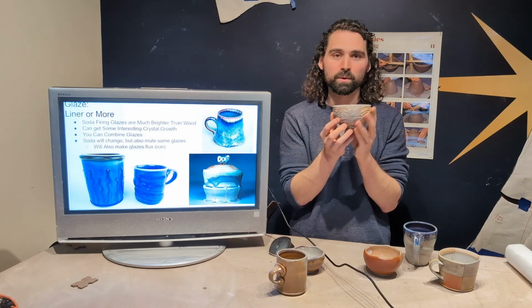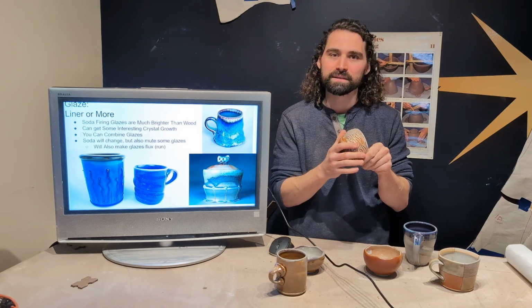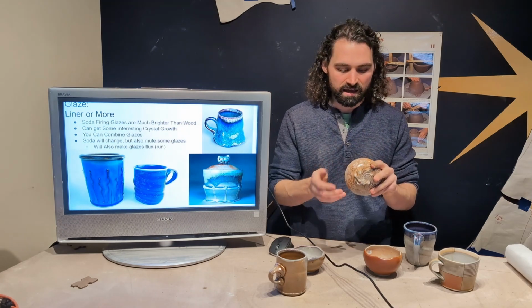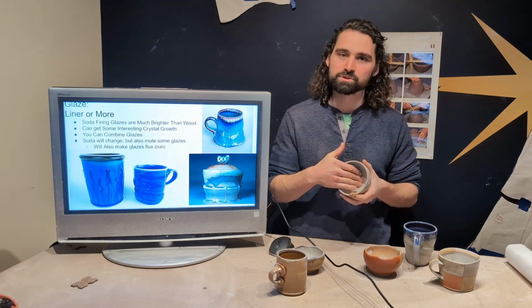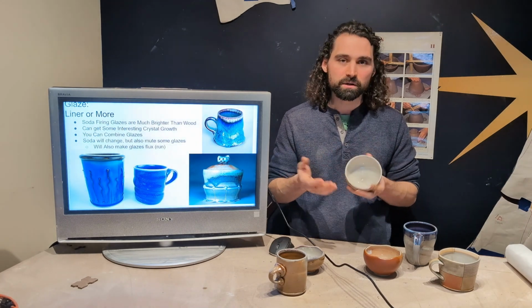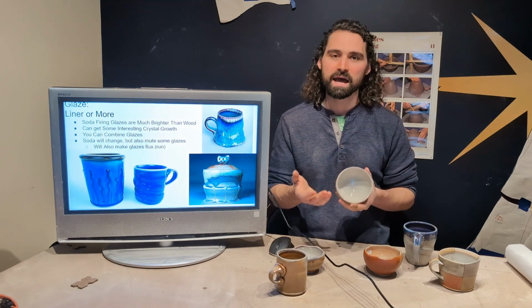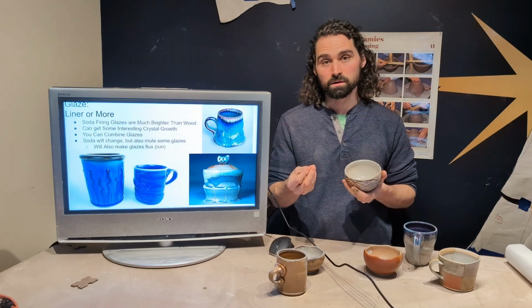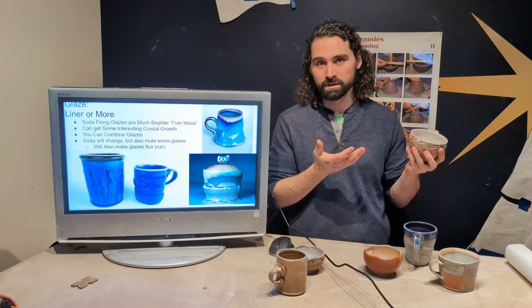If you know you're going to be using a flashing slip on the outside of your pieces, then I would urge you to liner glaze with a Shino glaze. Shino glazes often have soda ash in them, what we use to put into the soda kiln.